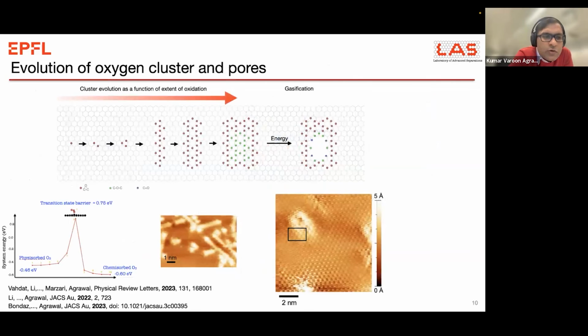Without going into a lot of other detail, I will just quickly summarize this here. What we showed was that when graphene is exposed to a reactive oxygen, in this case we were using ozone, what you first form is an epoxy group. Essentially, it goes through an energy barrier. This is essentially the thermodynamics of the reaction. You have to spend about 70 kilojoules per mole of energy to make this single epoxy graft onto the graphene.